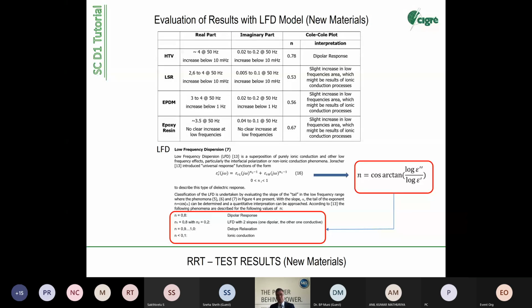But we are not at this target with the available devices on the market. So this is how it works, and this is the lessons learned from all of this: to get this in a device and to standardize the method of evaluating the dielectric response. Coming back to the evaluation of the round-robin test, the HTV showed more or less a dipolar response. LSR, and this is a surprise, showed a more conductive response, which is a surprise at the beginning, but we know there are fewer interfaces inside, so we don't have the interfacial effects so dominating. Epoxy resins tend more to be dipolar, but they also have a contribution by ionic conduction processes. So with these figures, you can really assess the material and see what's inside your material.